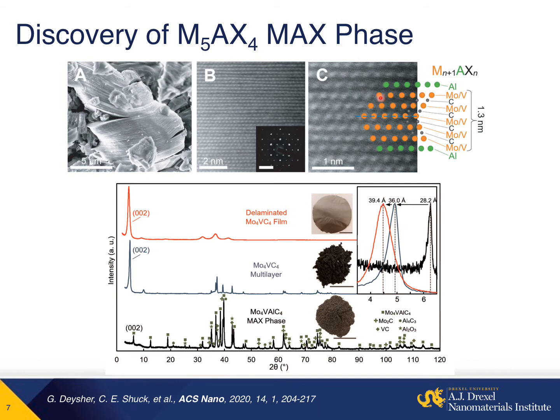And it looks like within each of these rows that it's a solid solution, so you have molybdenum and vanadium occurring in both. Now, after submerging this MAX phase in hydrofluoric acid for 8 days, we were able to successfully remove the aluminum layer. So you could see the 002 peak shifts to the left as we have intercalated water, and then we use tetramethyl ammonium hydroxide to delaminate it. So you can see that the color of the powder goes from this very normal gray to a black and then to a dull gray film after vacuum filtration.